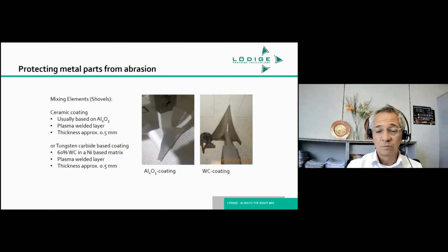So we've looked into other various options, and one option is to apply a tungsten carbide coating, which is basically 60% tungsten carbide embedded in a nickel matrix. And this again allows you, with the plasma welding, to apply a very thin layer to follow the contours of the mixing tool. And the one big advantage of this coating is that it's ductile. It's ductile, so the impact of foreign bodies cracking or breaking of the coating is severely reduced. And this helps then to prevent metal contamination from getting into the product.